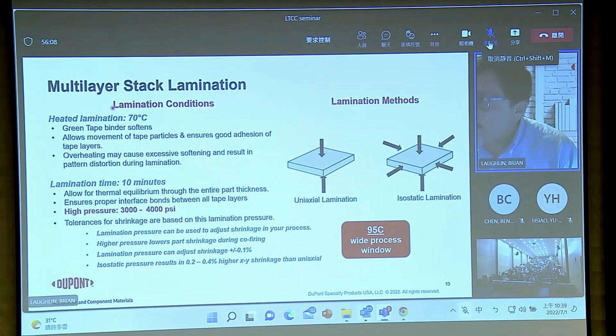And so once you get out of that, it's still unfired, it's in its green state, but all the layers take on a tack and the registration that you have carefully put in there. And there's some ability to change the green to fire shrinkage by the lamination pressure. 95C particularly has a wide process window where you can use this lamination pressure to change the shrinkage by a couple tenths of a percent.